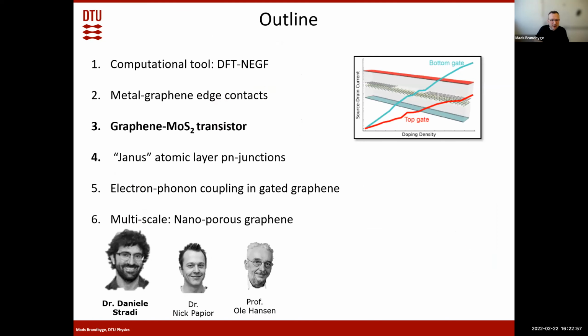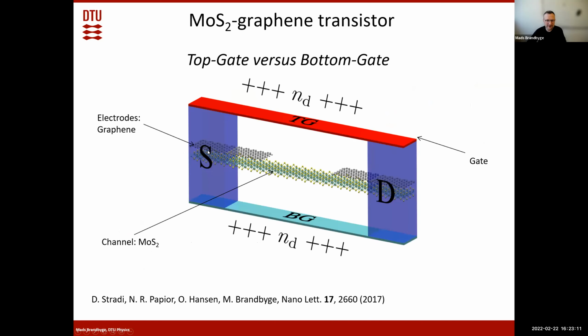Now let me switch to a transistor, to an actual device. And here we are considering a graphene MoS2 transistor. So MoS2 is a semiconductor, so that could make a semiconducting channel. And since graphene is a semi-metal, we could use that as electrodes. So here we're looking at a source and drain where we are overlaying graphene with the MoS2. And then, to make it a transistor, we put a gate. It could be a back gate, or it could be a top gate. And in the first place, you might think that it doesn't matter if I gate it from the back or from the top.